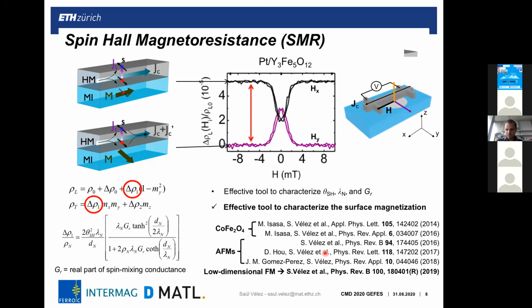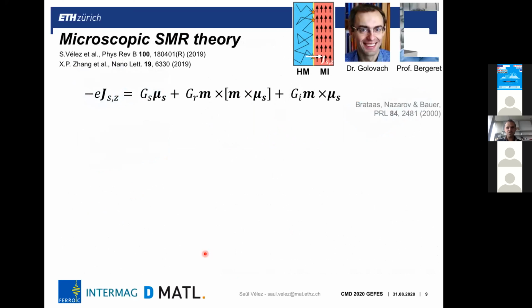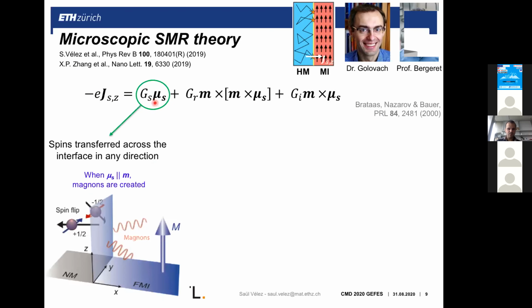So this is a summary of some of the work that we performed over the last years, and I will talk in particular about the exploration of this effect to detect the magnetization of a low-dimensional ferromagnetic material. The question is that the spin Hall magnetoresistance theory was essentially made phenomenologically, and typically only the real part of the spin mixing conductance is considered. Now if you think about the spin transport across the interface, you have three components in the spin conductivity across the interface. The first term here relates to the excitation of magnons in the magnetic insulator.